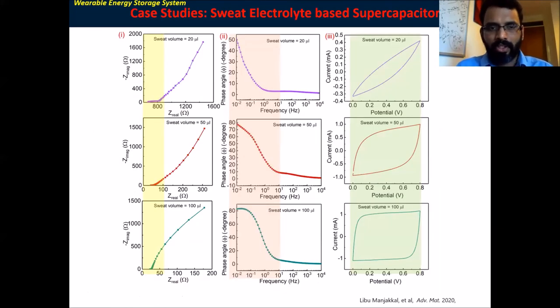So as I mentioned, it depends on the person, on the physiological condition, on the disease, or on the place. For example, in Glasgow, it's always cold, so getting sweat is very difficult. So I carried out measurements with different volumes, starting at 20 microliters. You can see that at 20 microliters the resistance is very high, 800 ohm. But as the volume of sweat increases, the resistance is reduced, and the phase angle, which relates to capacitance, almost reaches minus 80. With 100 microliters, you can see an almost perfect rectangular shape. So the volume of sweat is highly important.